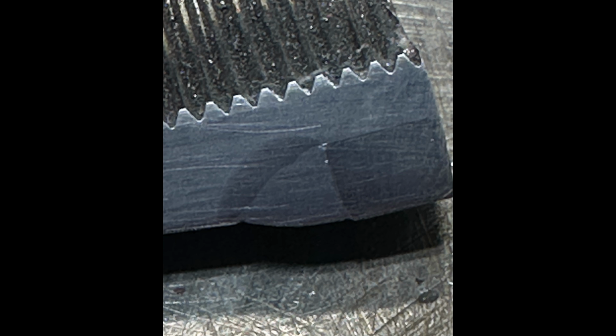There's a lot of things I don't like in this. So the first thing being on the right side, that plate has almost a straight line. There's a clear lack of fusion starting at the root going all the way down on that right side. And this just doesn't look good. Compared to the 2-pass TIG weld, it has about the same lack of fusion. It's just the cavern per se isn't as big, but it's not really that much better. The wetting out on the sides is basically non-existent. Don't like it. You don't generally want to see this.